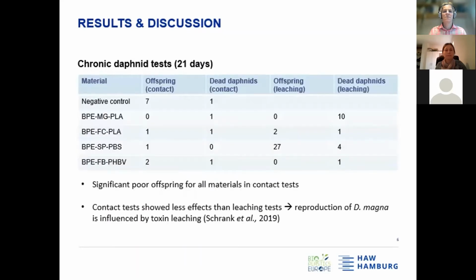In this table you can see the results for the chronic daphnid test with a duration of 21 days. And as you can see, during the chronic tests, a significantly poorer offspring was observed for all materials in contact tests.